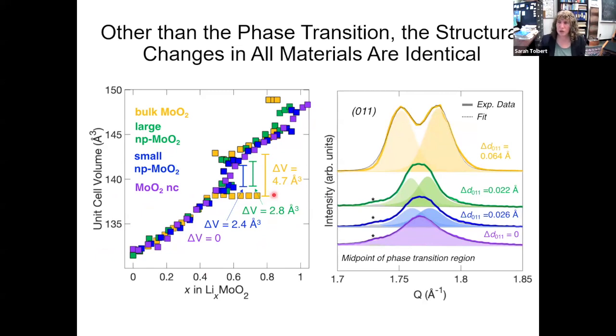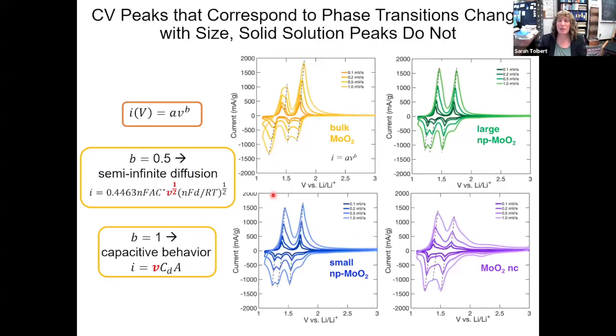So we can quantify that using electrochemical kinetics. And if you have not had a lot of chemistry, just close your eyes for about 30 seconds, and then we will get back to you with things that are simpler. So it turns out that when you take cyclic voltammetry curves, you can sweep the voltage at different rates. And if your material behaves sort of Fickian semi-infinite diffusion, you would predict that the current that you would measure varies as the square root of the sweep rate, or the sweep rate to the 1/2 power. For a capacitor, it should vary linearly with sweep rate. And so we can measure this exponent and say, for any given material, is the current that we measure more like a capacitor or more like a battery? So 0.5 is a battery, 1 is a capacitor.